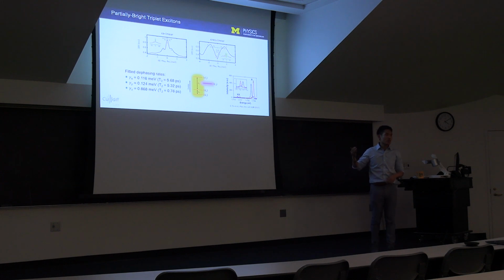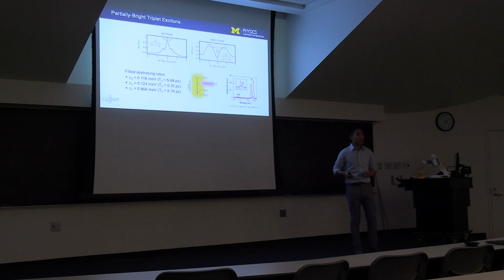This is because the emission is quenched by this dark state underneath. And because we see signatures of optical triplet coherences in our one quantum spectra, we should in principle be able to generate and measure coherences between the triplet states as well. These intertriplet coherences should show up as sidebands in zero quantum spectra. First we took zero quantum spectra with collinear excitation, but we didn't see any clear sidebands corresponding to coherences between states x and y. This is because omega 2 is very small, so it's hard to distinguish those sidebands from the central zero mixing energy peak. But we did observe many vibrational sidebands, so I have some extra slides on those if you're interested.